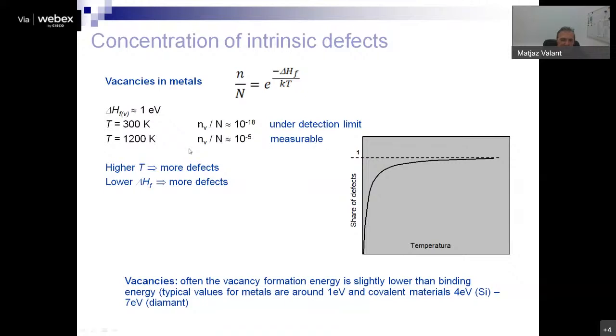Now imagine that we then immediately cool down such a slab to room temperature. If we don't allow a new equilibrium to take place, then due to kinetic hindrance we would still have all this high number of defects at room temperature, and such a material would have significantly worse mechanical properties due to this high concentration of defects.